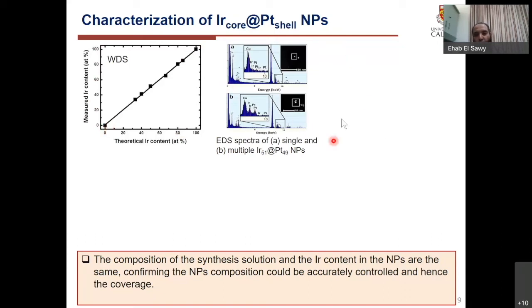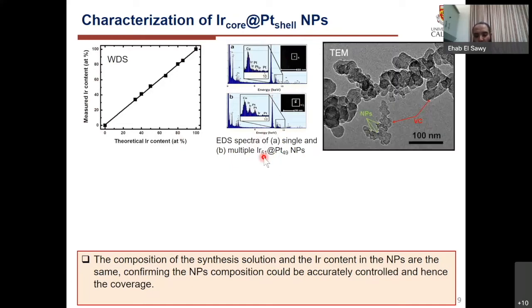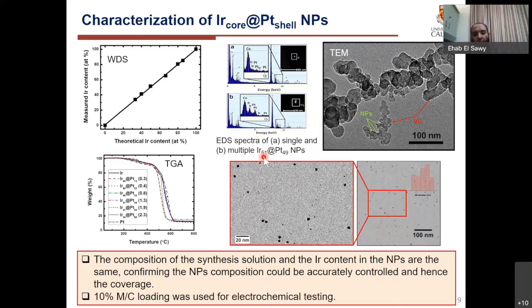And to confirm this more, we did EDS on TEM on a single particle or a cluster of particles, and the composition came very close to the desired composition. Then, for electrochemical measurements, we loaded these nanoparticles on carbon support, Vulcan carbon, and confirmed the loading using TGA, to confirm that we have 10% metal loading on the surface.